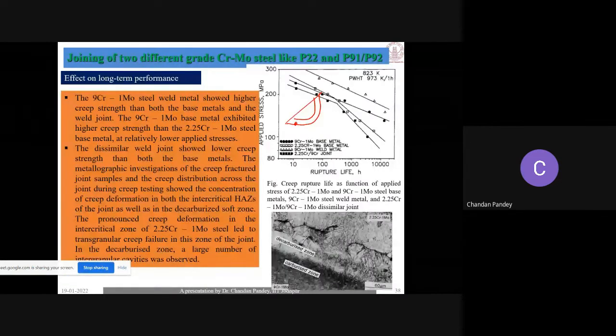So we get the failure either from the region of that intercritical heat affected zone, or here, due to the post weld heat treatment, you will get the formation, not in the CGHAZ, just near the interface, of that soft region. So either we get the failure from crack initiation or failure from the region of the soft zone. Here this is the published work. In that we get the failure in the region of your soft zone that formed just after the post weld heat treatment, and we get the failure after 10,000 hours of the service period.